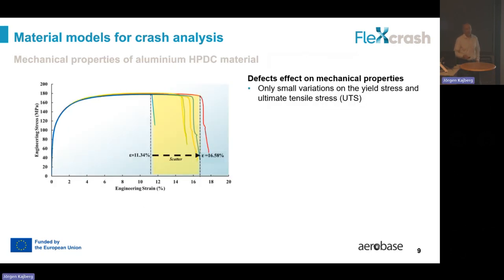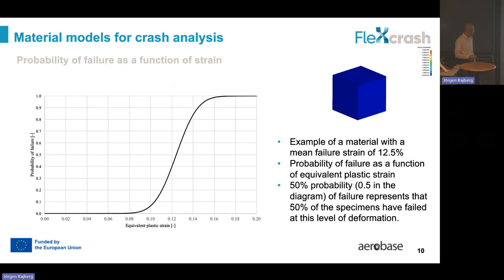So if we look at the mechanical properties of high pressure die casted material, this is a typical stress strain curve. If you test a number of specimens, you will see that you have quite small variation in the yield stress and ultimate tensile stress, but you have quite large variation in failure strain. As you can see in this example, you have a variation between 11 and 16.5%, and you need to take care of this. Of course, you can be very conservative and design your system for 11%, but with more sample testing, your lowest value will go down more than that. And that's the reason why we have introduced something called probability.